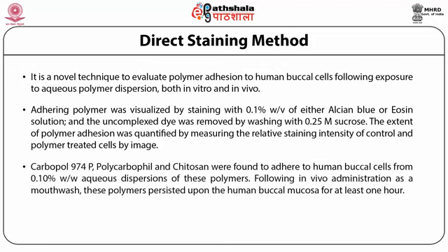image analysis. Carbopol 974P, polycarbophil, and chitosan were found to adhere to human buccal cells from 0.10% weight by volume aqueous dispersions of these polymers.